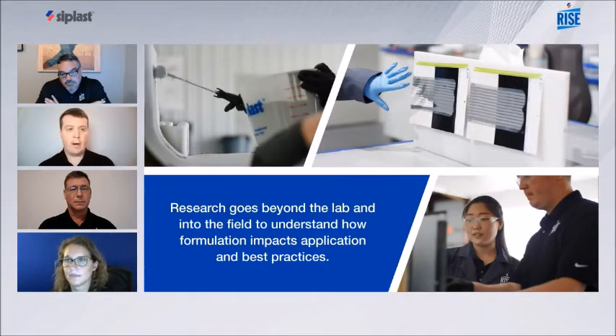You invert it for 24 hours, and you see what kind of sag you get from your product, whether it's at 50, 40, 30, or 20 mils. So, and you can see how that related to when we went out to the roofing school and did some hands-on application.